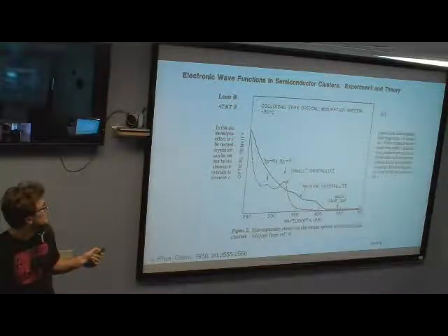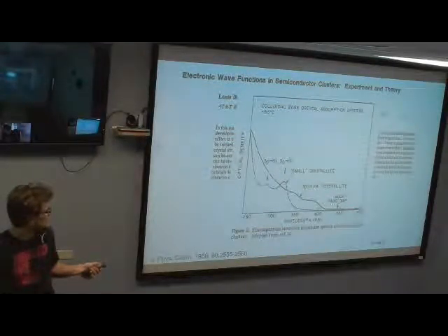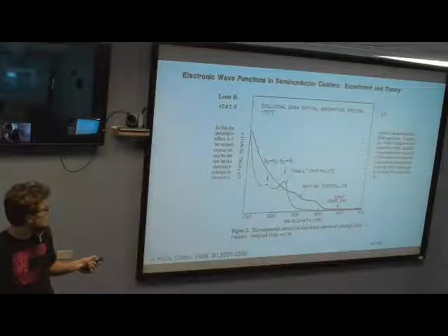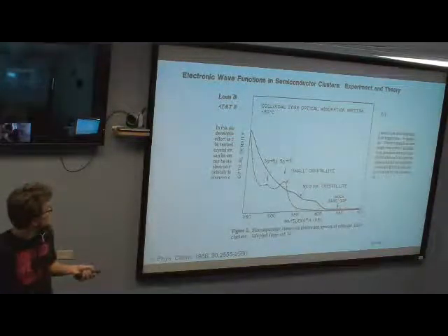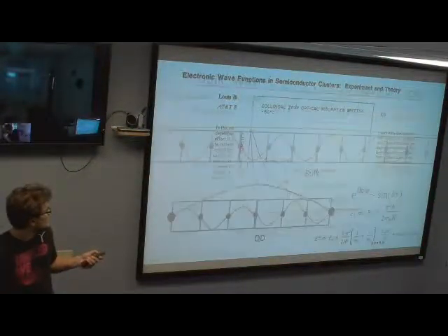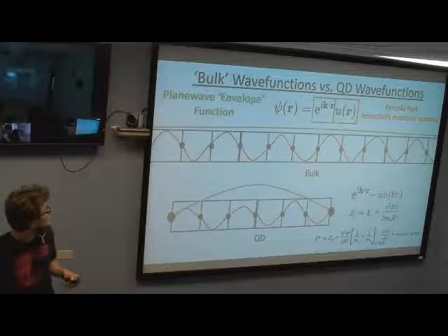So this represents the bulk band gap for, what are you looking at? Zinc selenide, some sort of system. So this would be a bulk material. And then if you make a smaller, medium-sized cluster, as they called it, you see absorption increase and then blue shift, and even more blue shift. And the theory I use to try to describe this, I summarized in one slide here.